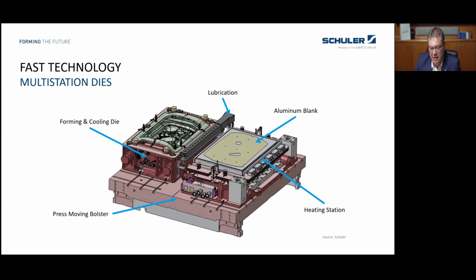On the next page, you can see also the first die. You can see that we have selected a more complicated part for forming, which is a door inner, which is a very well-known part or very well used for aluminum, because most of the OEMs make their doors out of aluminum, and the inner door is always a challenge. And so we have selected the inner door for the next part. And here you can see on the right side the setup for the heating plate. In the middle, you can see the bar for the spray lubrication, and then the forming and quenching die with classical drilled holes for cooling down the pressed part.